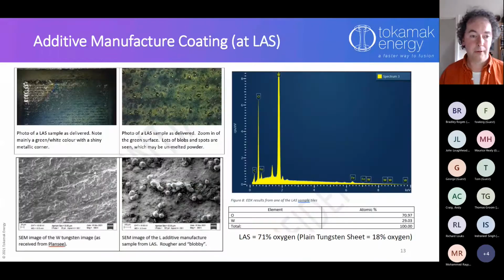If we have a look at them in close-up, this is the sample. In the top corner here, this will be the last bit to be deposited. They use an argon sheath gas to stop oxidation of the surface, which works fine when you're actually depositing, but we think probably what's happened here is as the head's moving across the sample, depositing tungsten like a raster going across, it probably ended up over here with the argon sheath gas that managed to still protect this from oxidation, but because the rest of the sample was still hot in air, it's oxidized to this green color, which is characteristic of tungsten oxide.